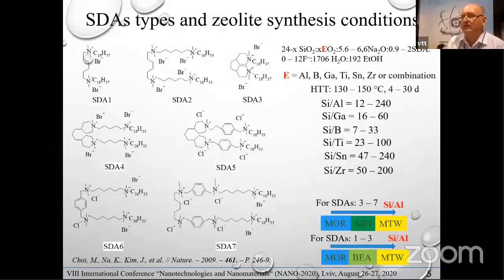For creation of hierarchical materials, different synthetic approaches can be used. There are many methods of preparation of porous materials with the presence of mesoporosity, which can be used as transport mesopores for better catalytic activity and better accessibility of active centers. But one of the, sorry for technical problem, we synthesized more than 50 different compounds with different structure. For all the structures, there are some characteristic details: at the end of the molecules there is a large hydrophobic chain.